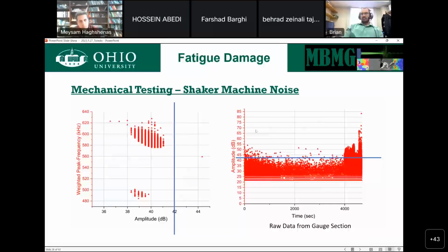Now, if we look at the data on the right, this is the raw data collected. We're getting a bunch of noise from the machine. If we put that 42 decibel cutoff on it, we still have some information early. We definitely have information as we get towards the final failure of this sample. So we lose information likely because it's noisy. We're throwing away information just by using a threshold method, but we still get an idea of what's happening.